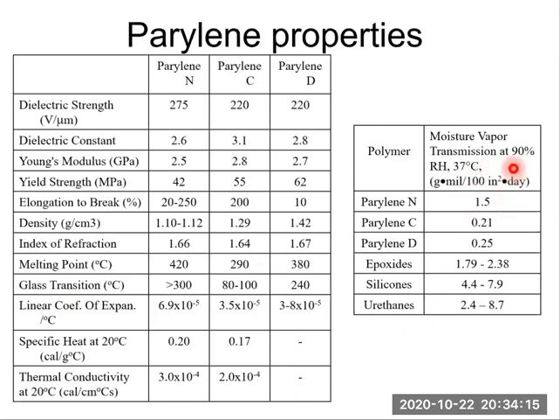Moisture vapor transmission at 90 percent relative humidity and 37 degrees C. We can observe that parylene C has the lowest moisture vapor transmission. It has the smallest moisture transmission rate, 0.21. It's the smallest among these polymers. So parylene C is a good moisture barrier. Note that the moisture transmission rate is small, but not zero.